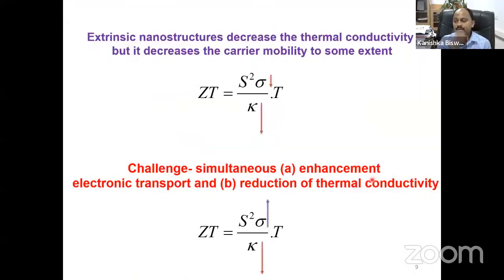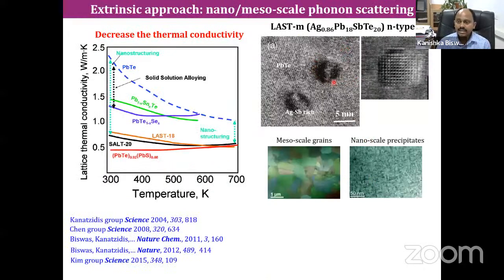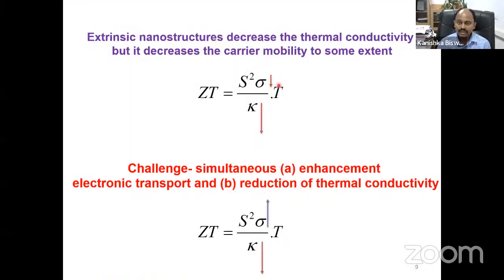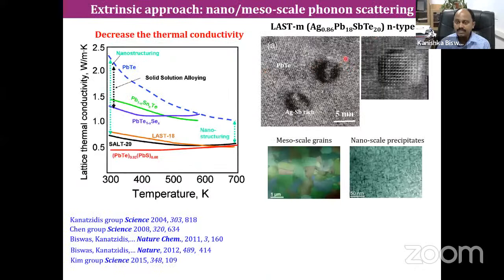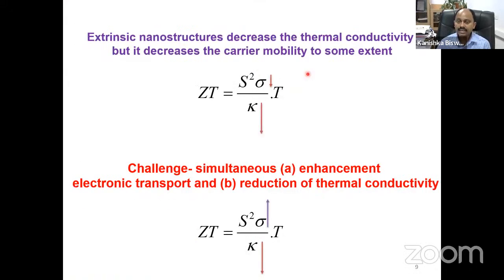Then when I came back to India, I thought, okay, this extrinsic nanostructuring scatters phonons heavily and terribly decreases the thermal conductivity. But at the same time, these are foreign elements, right? And once the lattices are completely mismatched, the boundaries of these precipitate-matrix interfaces have a huge amount of dislocations and defects, so they actually scatter the electrons and holes. So we always compromise on the numerator of the ZT, and we get a suboptimal ZT by this extrinsic nanostructuring approach.